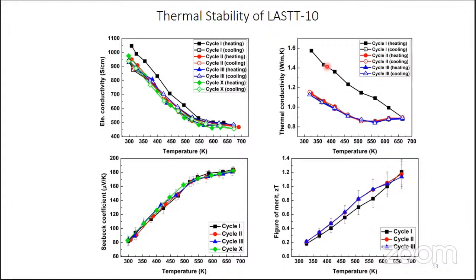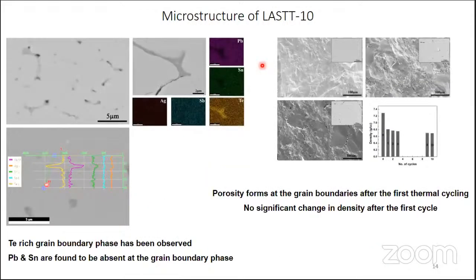But this is not an equilibrium microstructure or equilibrium chemistry of this material. Whatever we got is a pseudo-stable microstructure. So then we analyzed this microstructure and the phase diagram very thoroughly. What we understand is that this material, LASTT-10, this stoichiometry, has the tendency to form some kind of secondary phases like this at the grain boundary. So this is the basic microstructure we want, the required phase. And then apart from the required phase, you end up with a secondary phase here.